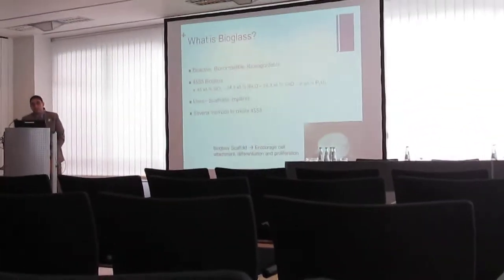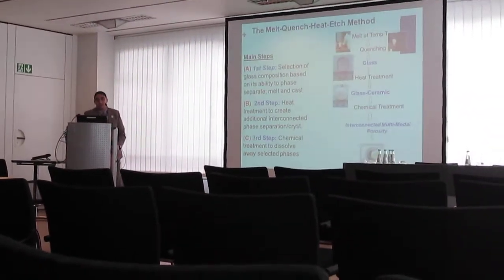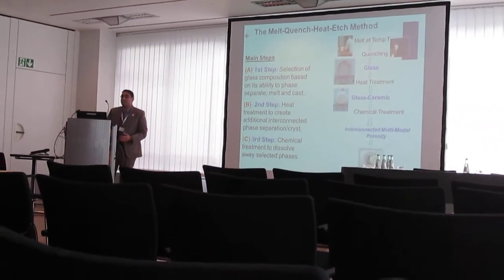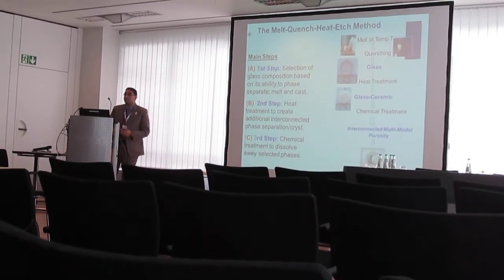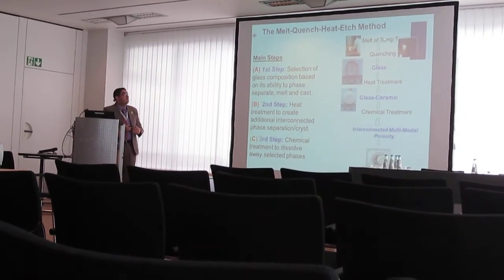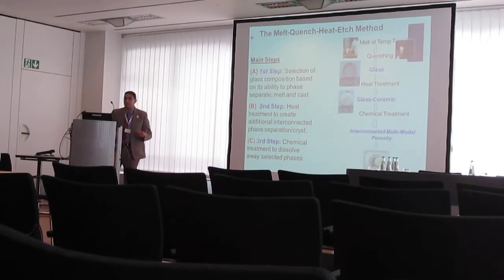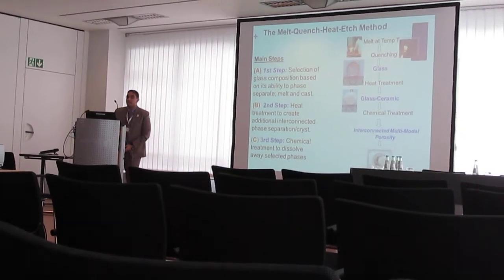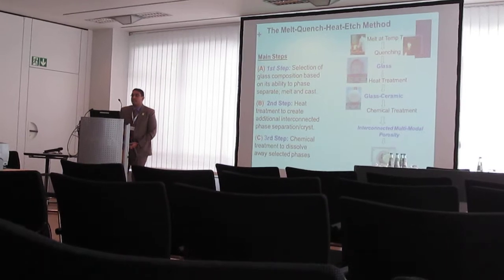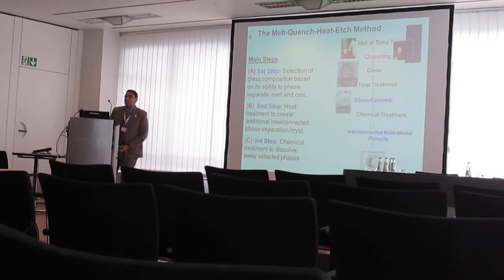There are many different methods to create 45S5 bioglass. One of these is the melt, quench, heat, etch technique, in which you start at a temperature T and quench to create the glass, then heat treat it to create the glass ceramic, and finally chemically treat it to introduce porosity.